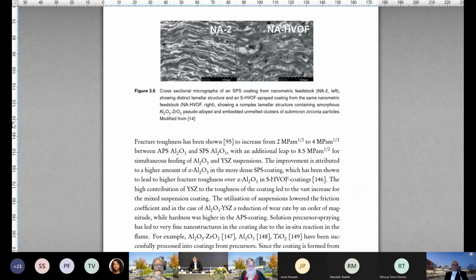It would seem like that, but as you noticed, I didn't have fracture toughness measurements in my thesis, and especially when it comes to these nano coatings, I would somewhat challenge the transferability of these values, because you measure crack length, and as we saw, the crack can stop in a cluster like this. Yeah. And then you get a high fracture toughness, but it doesn't mean that it has a higher wear resistance or that it couldn't be damaged afterwards. So it's an artifact of the measurement method in these cases, I think, since it's so characteristic, but then you look at the pictures and it's not necessarily a cohesive coating. Okay, thank you.